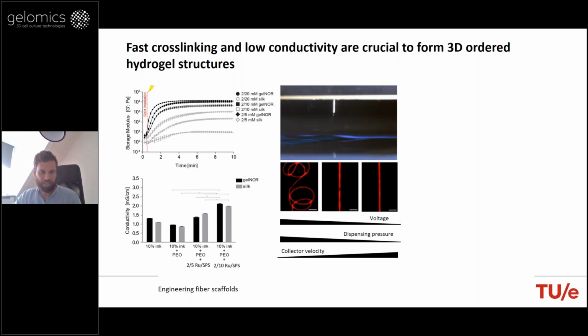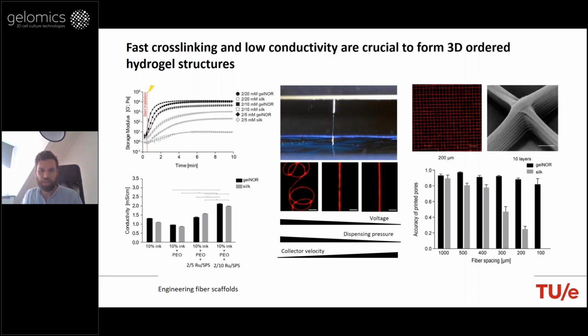In the central column of this slide, you see that we could, as I mentioned, achieve a stable jet formation, but that was after quite some tedious work exploring the influence of key instrument parameters on jet formation. In this case, we look at the voltage, dispensing pressure, and collecting speed in order to get straight fibers and be able to control the architecture of the printed constructs. And by doing so, we could achieve controlled laid-down fibers with different fiber spacings.